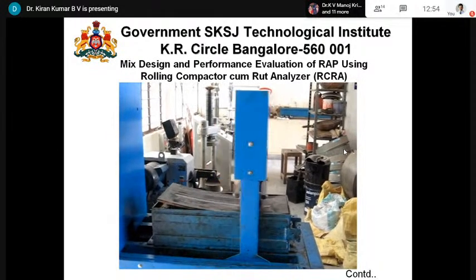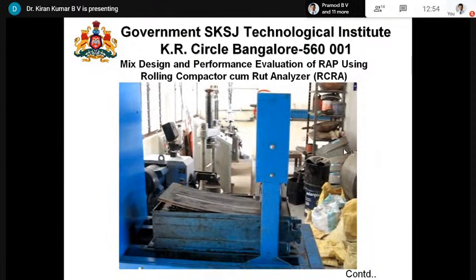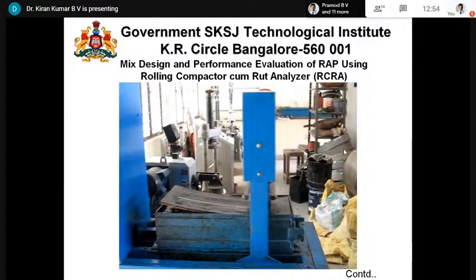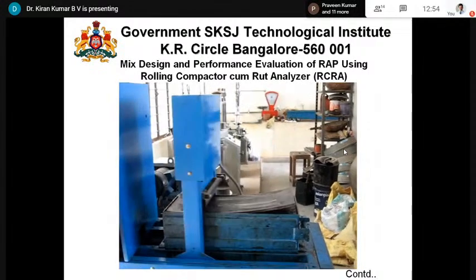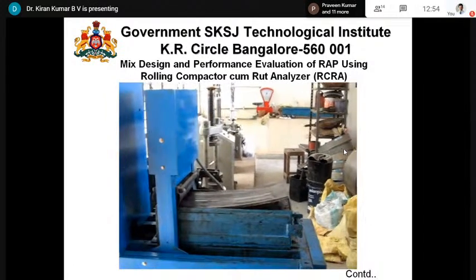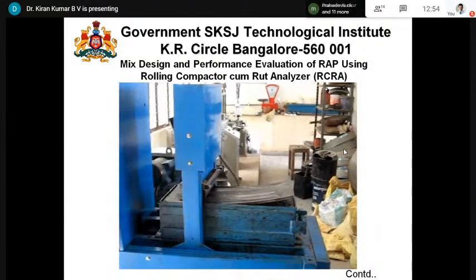After casting the slab for various binder contents, we have come to the optimum binder content by drawing the cores from this slab which is cast. Once this slab is cast, we have taken it out and taken the cores out of it to check the density as well as the binder content. With various binder contents, we cast this slab, and cores were taken based on their density value, air content value, VMA value, VFB value, voids filled with bitumen, and voids in mineral aggregate value.